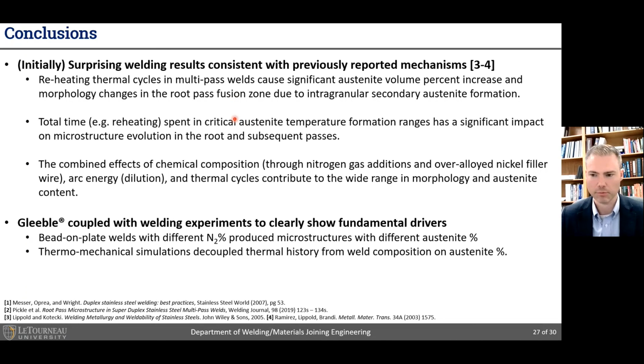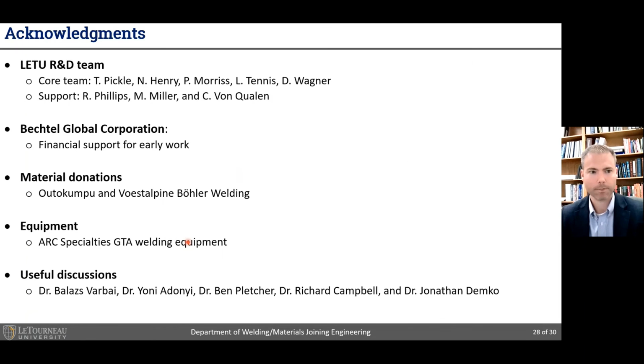And we really do need to bring all of these factors together: chemical composition through nitrogen gas additions, over-alloyed nickel filler wires, arc energy, and of course these thermal cycles, to really understand how microstructure evolves. And finally, we showed that using the Gleeble, we were able to couple not just the Gleeble for base metal evolution, but to actually bring in these welding bead on plate experiments to directly probe how both composition, in the form of the nitrogen shielding gas content, and the thermal history drove the subsequent austenite volume percentage.